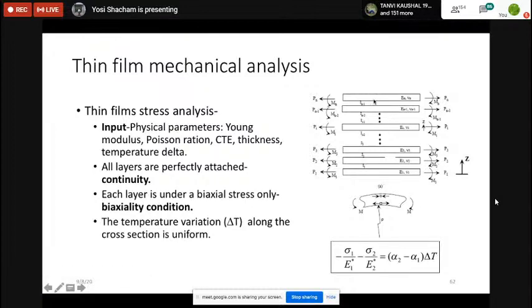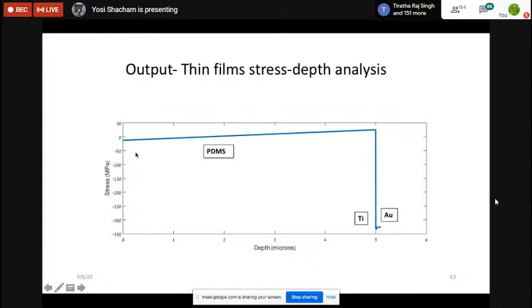That we can calculate the stress in this material, and because we want to deal with more than one layer, we develop it. This can be polymer metal. So we solve it for multi-structure. And then we apply this solution to calculate the stress in our materials. So this is stress versus depth. This is a PDMS, about 5 microns. And as expected, the stress in the PDMS is very, very small. You see, it's less than 10 megapascal.